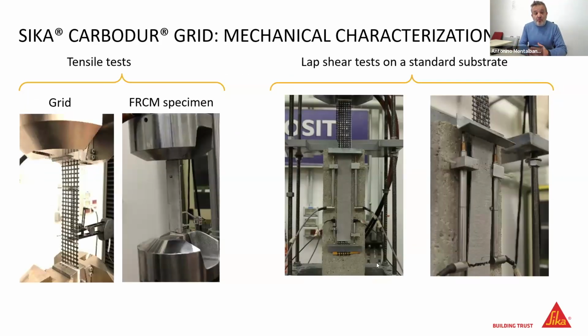The system is fully tested. We perform tests on the grid. We perform tensile tests on the FRCM specimen, and we did some lap shear tests for the characterization of the adhesion on a standard substrate. The standard substrate can be concrete, like in the picture you can see on the right part of the slide, or the standard substrate could be bricks, tuff, natural stones, for example.